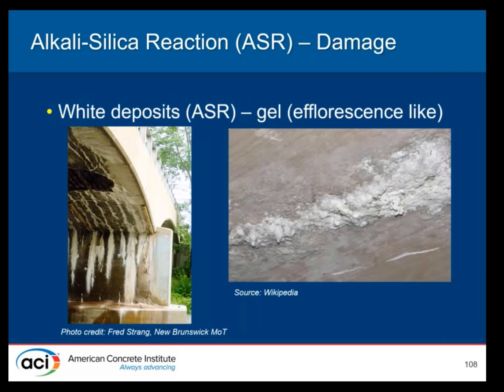So what does that look like? The ASR gel is typically a white deposit, efflorescence-like. And in unrestrained concrete, the cracks will develop into a random pattern, commonly called map cracking. Restraint cracks tend to run parallel to the direction of restraint, or parallel to the direction of the reinforcement, or vertically in a column. And the cracks may exude that white gel, which we just mentioned. Pop-outs may occur where individual pieces of aggregate have expanded and disintegrated beneath the surface. Typically, ASR reactions take time. In most structures, it's a couple of years after casting, but it could be earlier with some aggregates. And in some aggregates, it may not appear for 40 years.